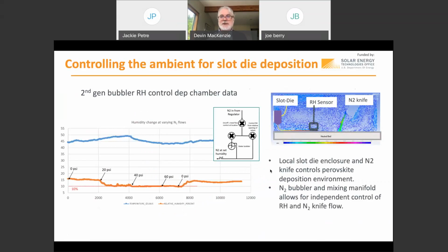It's important to know. And we developed an enclosure system. We've worked with what we'll call an air knife, a nitrogen knife. This shows the air knife with a circular, locally enclosed chamber in the box, because we only want to control the humidity and temperature right near the slot die head, and the flow right around the slot die head, to have consistent flow. Up to a full bubbler system, we could actually bubble water into nitrogen to get to a relative humidity. Relative humidity scales are calculated for air, which of course is 20% oxygen and some other stuff.